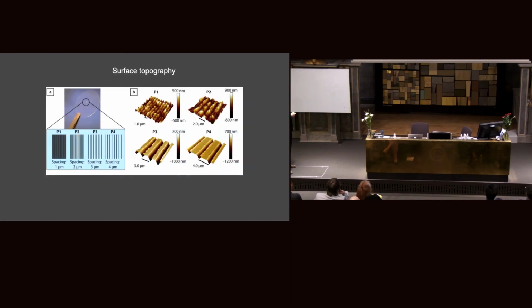So we got different surface topography: less spacing and larger spacing. The less spacing has more nano-shaped structure in it, more sharp or a little bit random. And the larger spacing, we have a more unified structure and patterns.